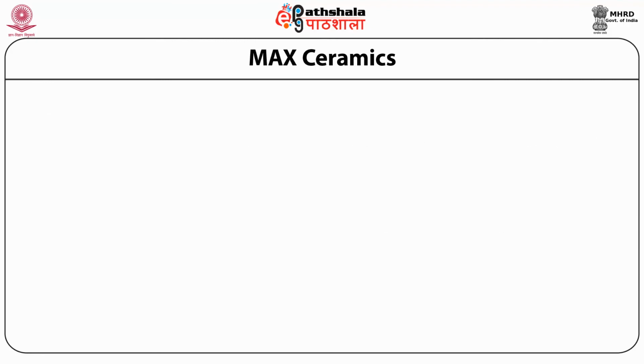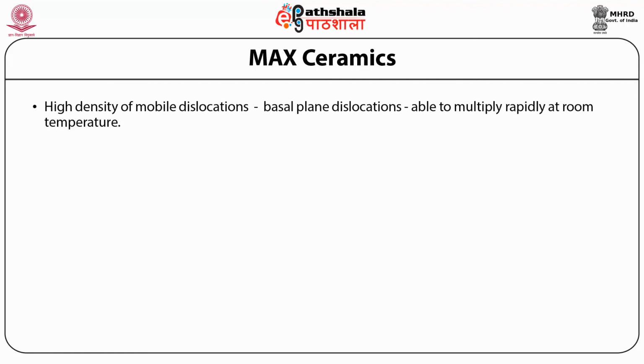The reason for this is the presence of a high density of mobile dislocations in the MAX phases. The dislocations are basal plane dislocations.